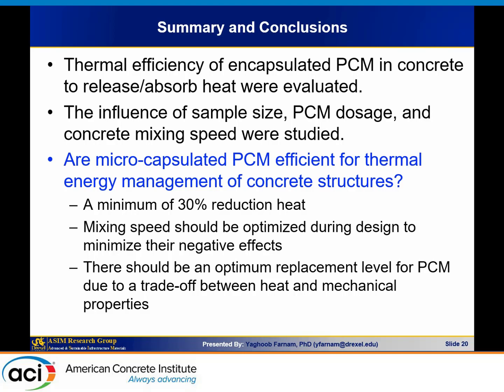And going back to my title, are microencapsulated PCMs efficient for thermal energy management of concrete structures? We have to be very careful. We have about a 30% reduction in the thermal performance. This is a minimum reduction that we get. It might be more than this. Mixing speed: we have to be very careful if you want to put PCM inside big trucks and make pavement out of that. It's going to stay inside the truck for 90 minutes. Mixing might break the shells.